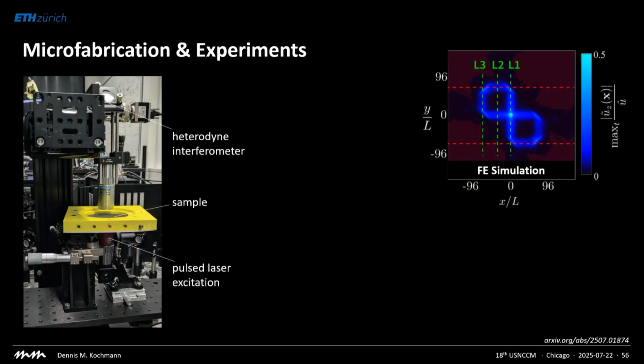And with this, we can build, we can test. This is the setup from our lab, where the sample is here in the middle. It's basically a thin silicon sheet, which you excite from below with a laser. And then we look at it with an interferometer from the top, which figures out the displacement, the out-of-plane displacement.